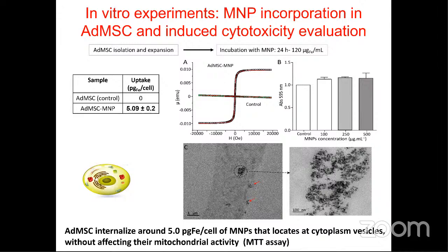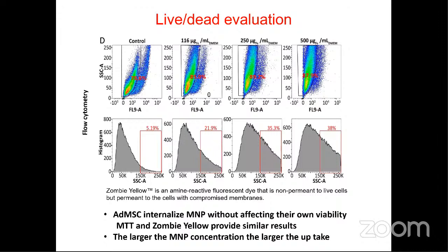I like this experiment very much because you can say, yeah, you have incubated with different concentrations, but you don't know how many particles are going into the cell. So how much is the uptake? It could be the same uptake. It is a possibility, but if we see the side scattering histogram, which is related to cell granularity, we see that this area starts to increase, and this increase is related to the uptake. This is telling us that the uptake is increasing. Although the uptake is increasing, the iron incorporation is increasing, we don't have much toxicity or loss of viability registered.